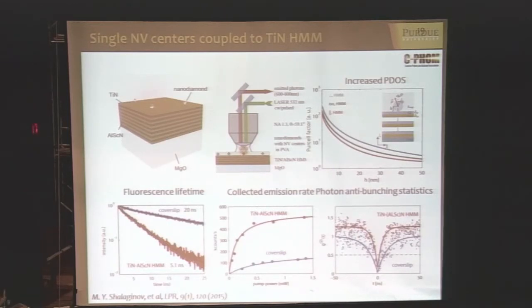Because of the hyperbolic nature of this metamaterial, the density of states could be increased. The closer to the material you are, the larger the enhancement - it could go up to 100. We indeed observed this increased rate of spontaneous emission, and that's what's needed - you want to get single photons at a higher rate. We get roughly 500,000 counts per second, a very high rate of single photon generation. To prove they're single photons, we measured this G2 correlation function, which goes well below 0.5, usually considered the requirement for a single photon source.